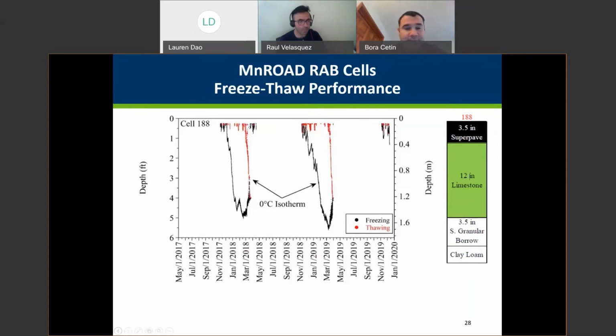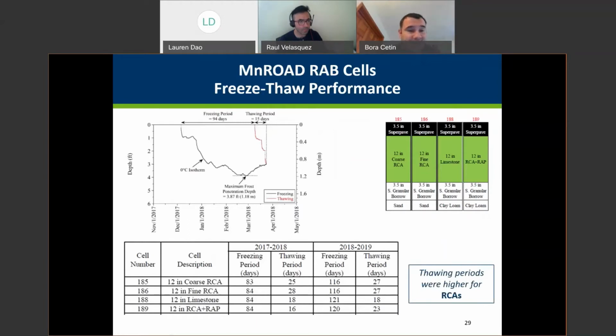Next slide, please, Rob. And here again are the 0 degree Celsius isotherms. Here we determine the maximum frost penetration depths, the freezing period for each material, and the thawing period for each material, and determine which material takes longer to freeze and which takes longer to thaw, which is very important. We summarize these for each year for each recycled base layer here. And as you can see, the thawing periods were higher for RCA, so it takes a little bit more time for RCA materials to thaw completely.